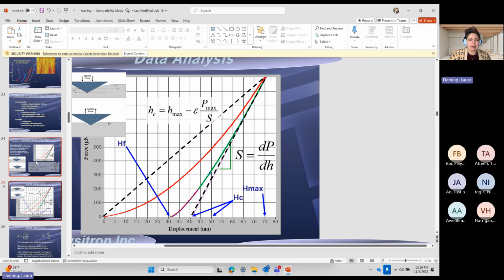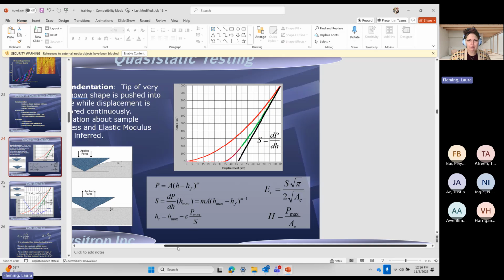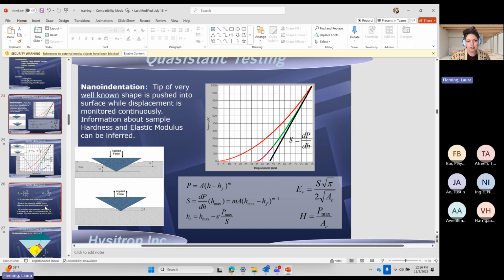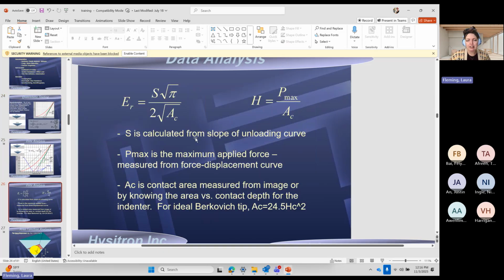Now, why does HC matter? So if we go back to this statement of tip of very well-known shape, it has to be well-known because the reduced modulus and hardness are dependent upon the contact area. So what that means is that if you have a perfect pyramid, which is what an indenter typically is, which we can also talk about all the different kinds of indenters and when you would use them, as you indent into the sample surface, if you take that pyramid and you cut it where the contact depth is, if you're looking at it, it's going to be a triangle. And from there, you're going to be able to calculate the contact area.